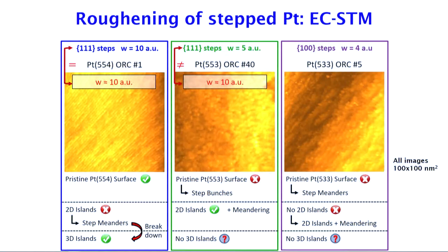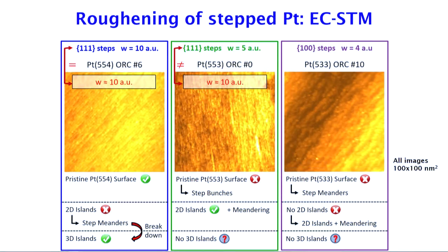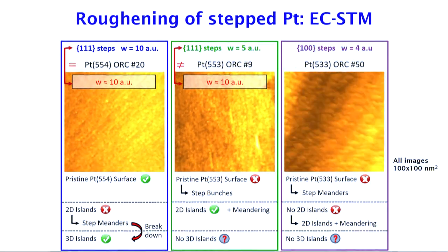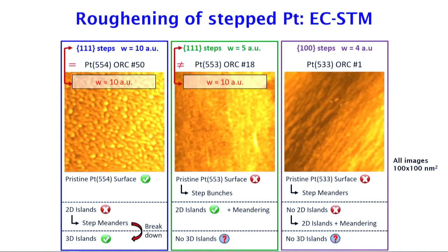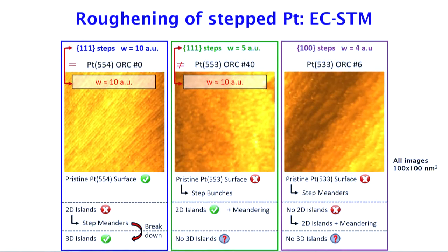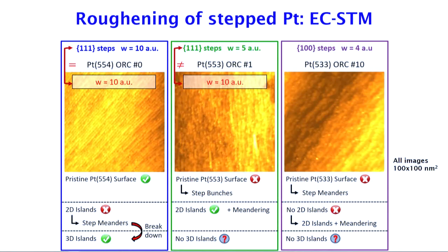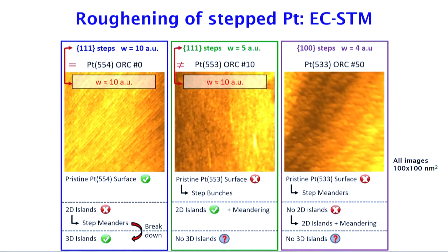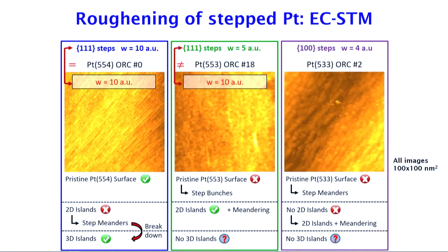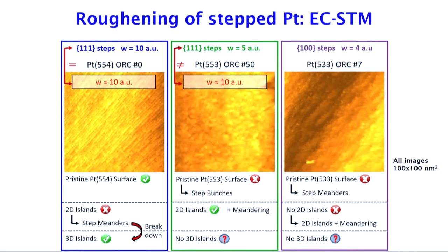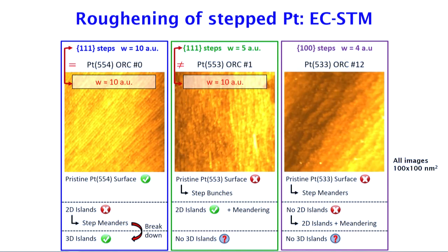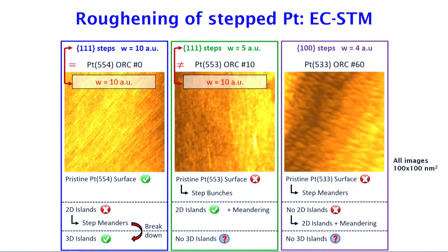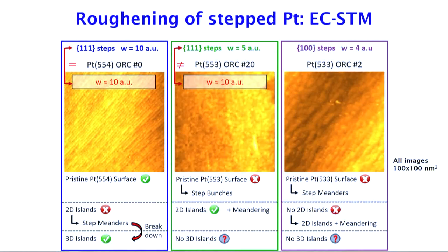and what is very interesting there is that very early on we see that the straight steps are highly unstable, they meander a lot, and at some point you will see that they even change direction. And this is something that you can also see in the voltammetry. I didn't show you that, but originally we have a peak corresponding to a single step geometry, and as you go through the cycling it looks like all that charge is transferred to a peak of another geometry, and in the STM that is accompanied by a change in the direction of the step. And again, we need to analyze this.